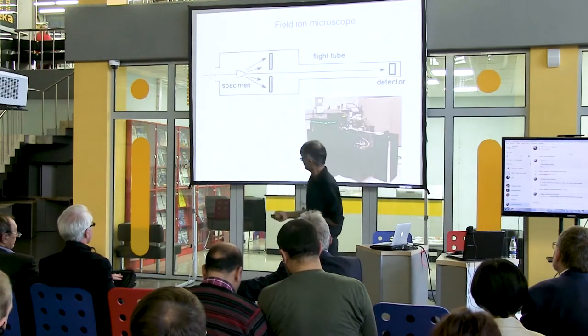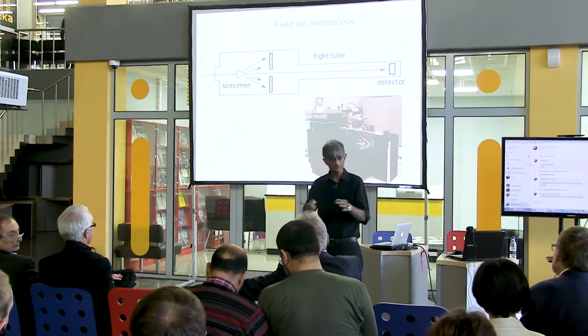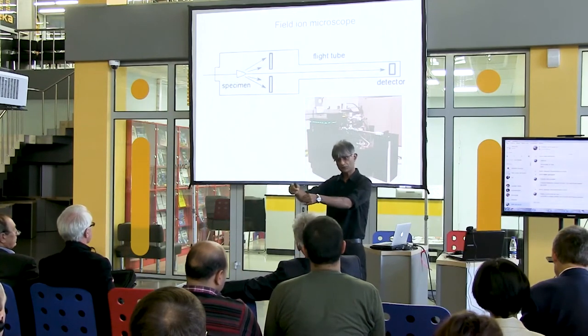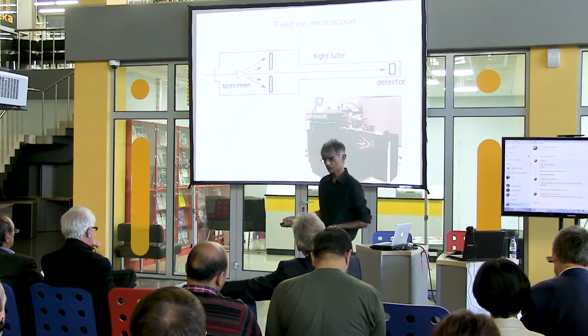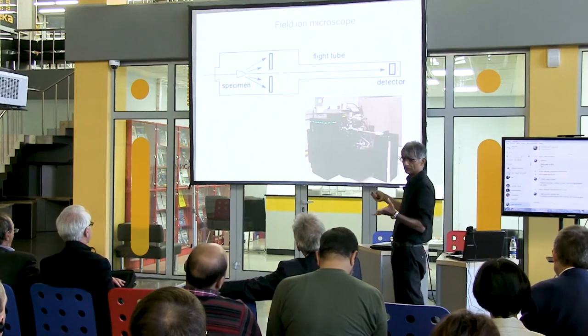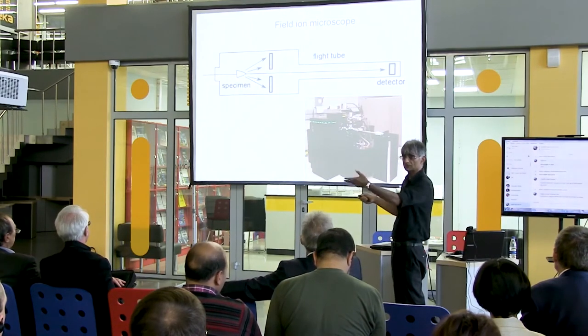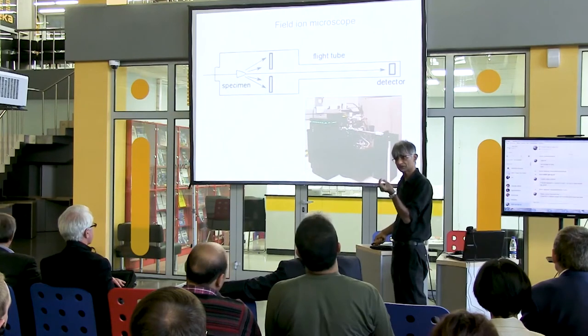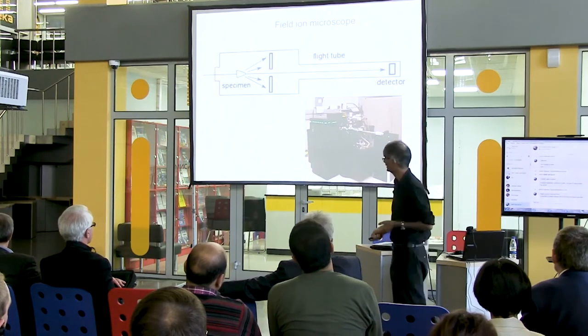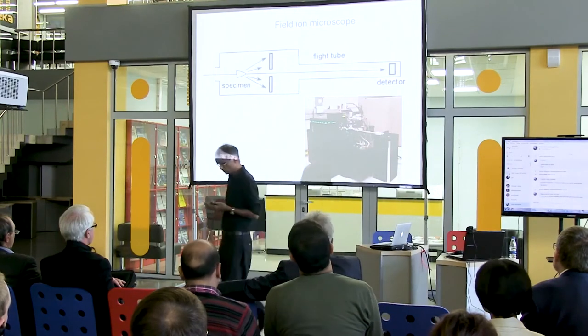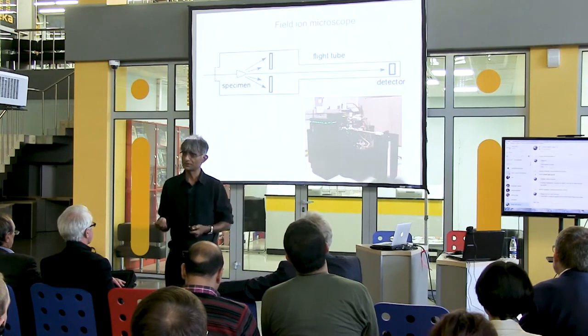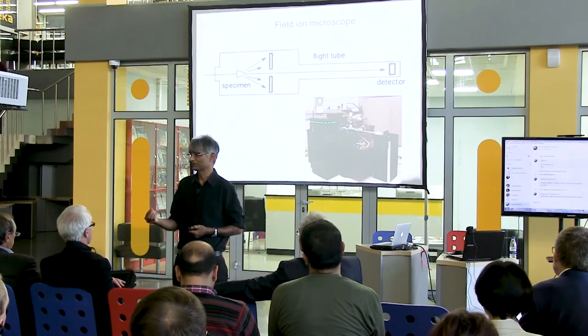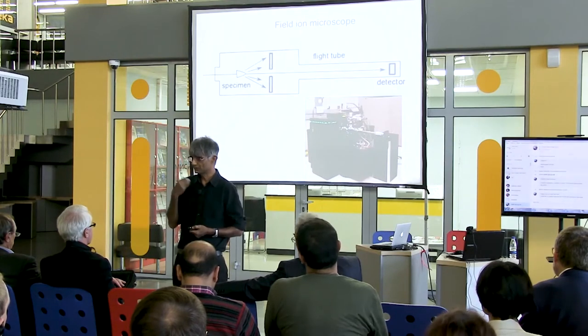The atom probe works as follows. You've got a specimen shaped like a very small needle, and you apply an electrical potential. You have some imaging gas which follows lines of the electrical field and gives you a magnification of about 10 million times. You can also apply an electrical pulse which will make an atom evaporate and then apply a time-of-flight mass spectrometer. So you can identify the chemical composition of an individual atom. The total amount of material ever examined in a TEM is 10 to the minus 5 kilograms. In this instrument, it is orders of magnitude smaller than that.